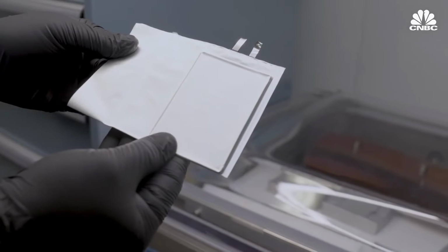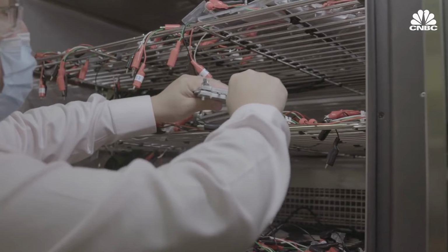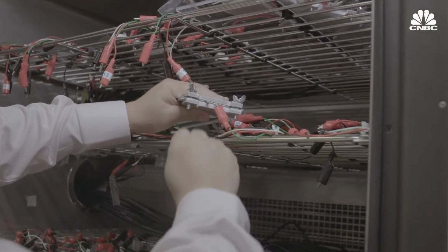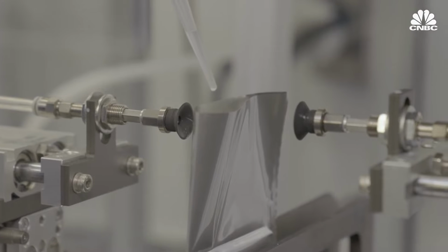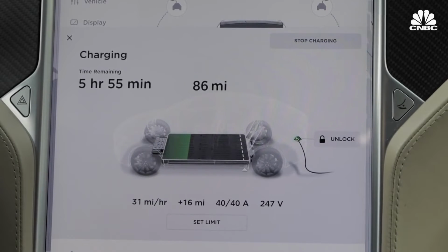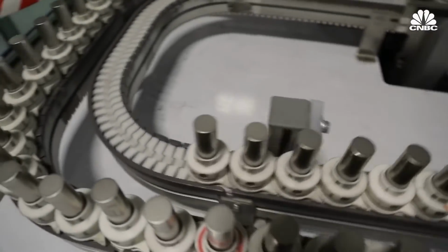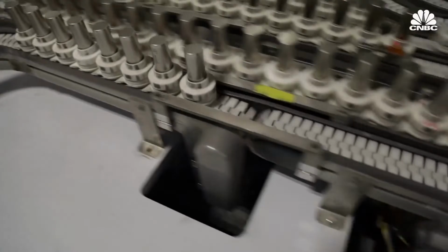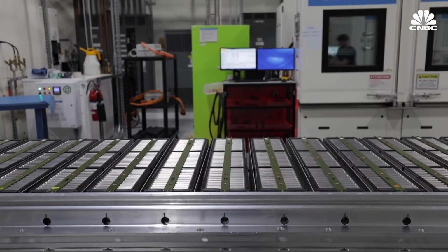The energy density of the cell using our cobalt-free cathode is twice that of the LFP. And in terms of the cost, we're almost about 30% lower than that of LFPs. Yet at the same time, this cobalt-free cathode meets and exceeds the performance that you would see from a traditional cobalt-carrying cathode in terms of energy density, which is the energy that you can pack in a certain weight or a certain volume. It meets the life expectancy of a traditional lithium-ion battery. And in terms of cost, it's almost about 35 to 40% lower than the cost of your typical lithium-ion battery.